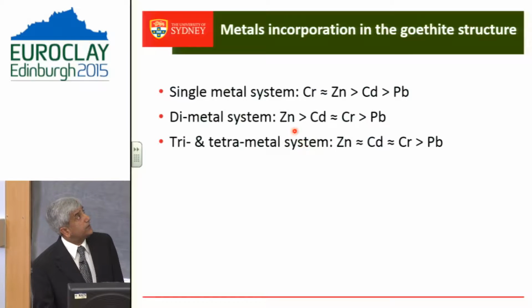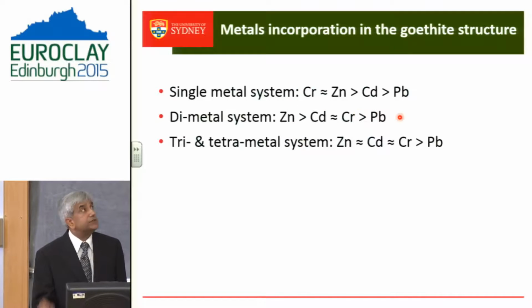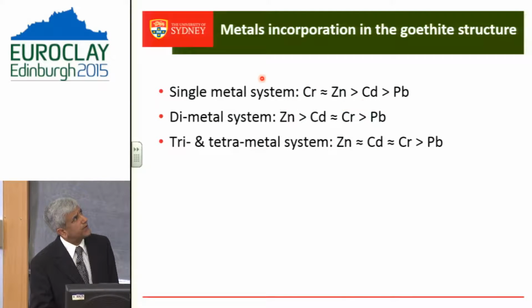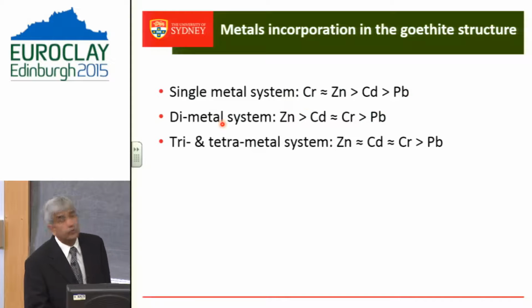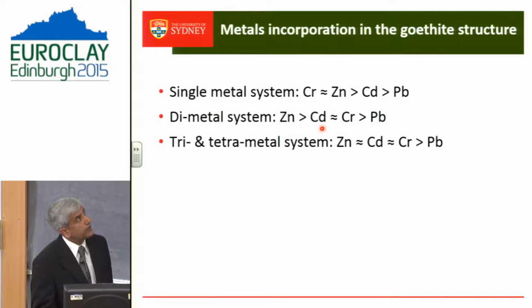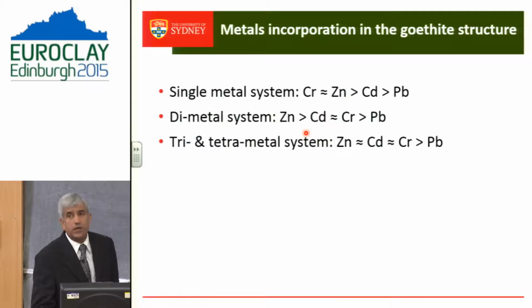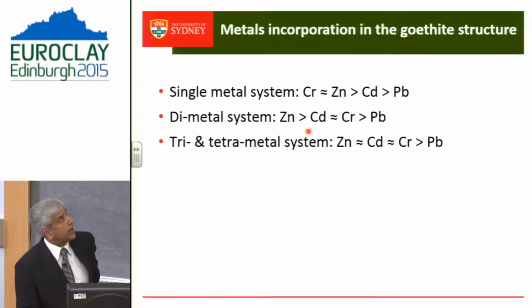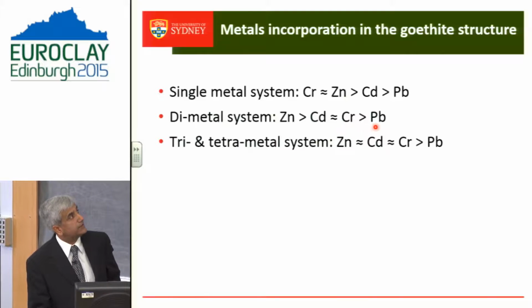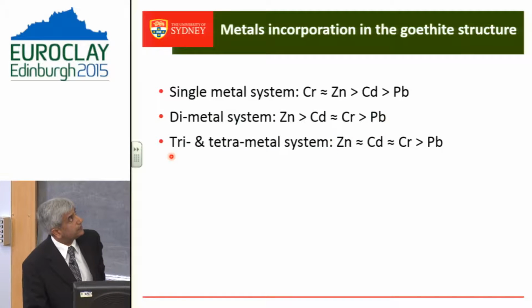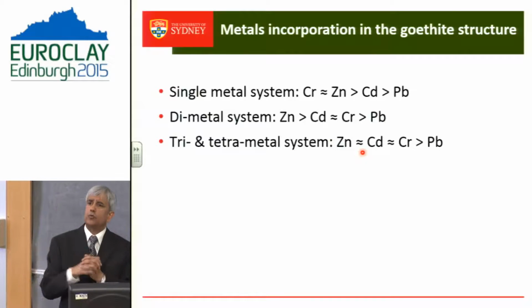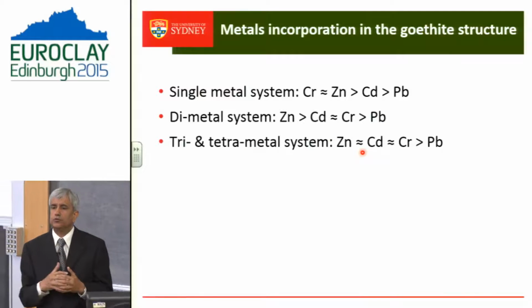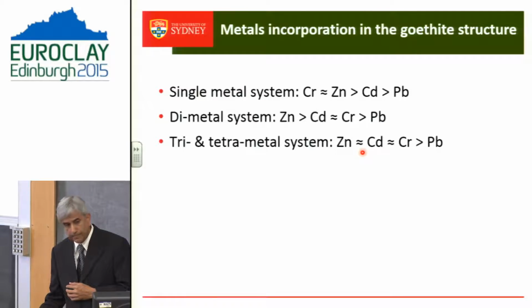The summary is that in single systems, the amount of metal substitution for chromium, zinc, and to some extent probably cadmium also, were quite similar, much greater than lead. When you combine 2 elements together, once again, zinc and cadmium were able to substitute, or the amount substituted for these 2 elements was much greater than lead. And in case of the tri and tetra systems, similarly, these 3 elements which get incorporated easily in single systems also got incorporated in the mixed system.